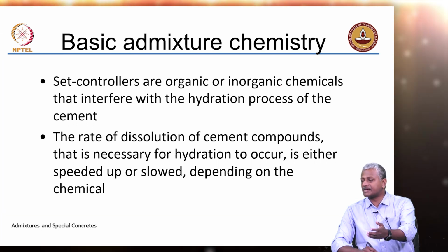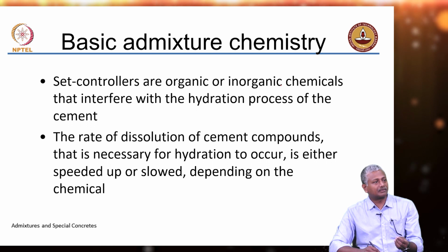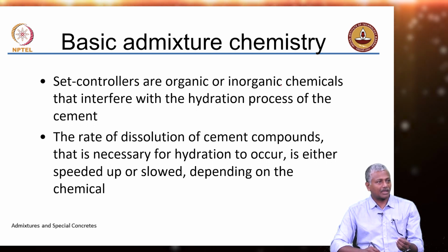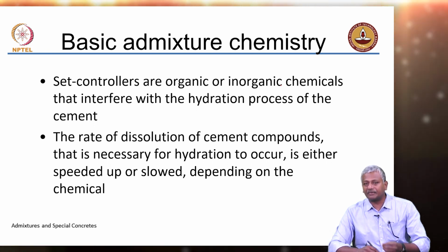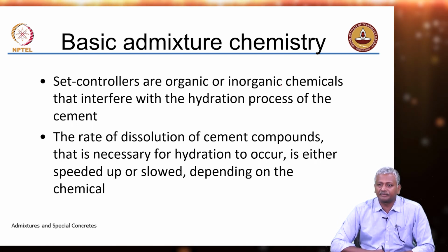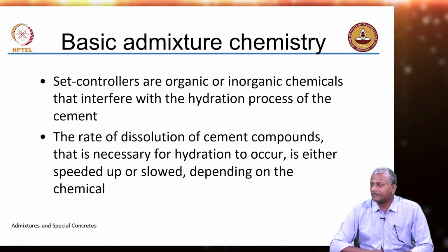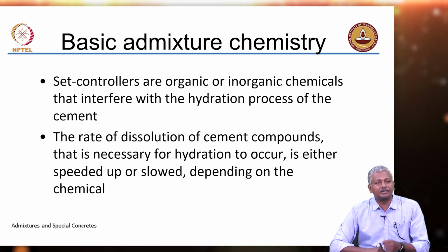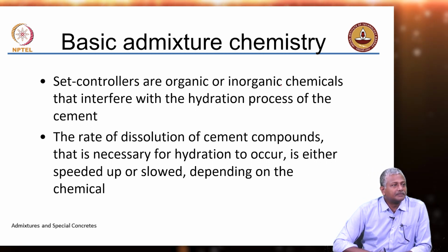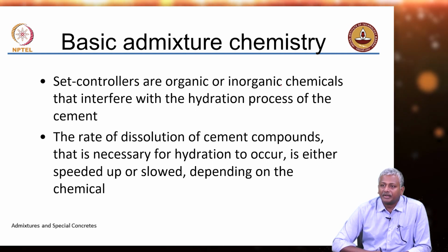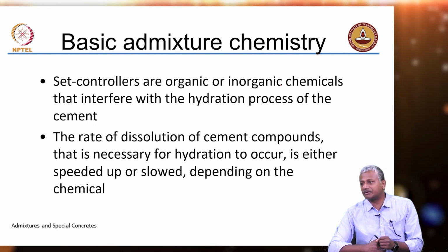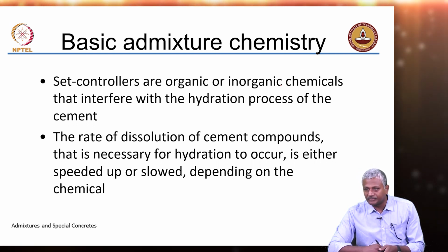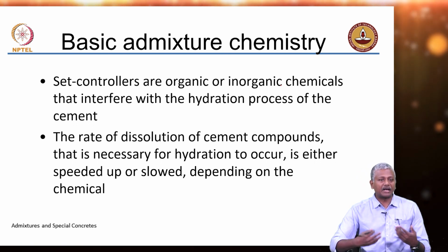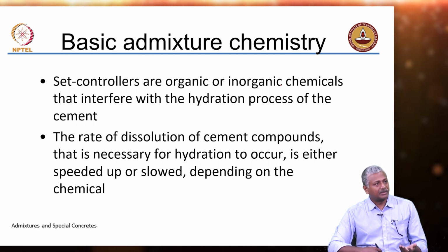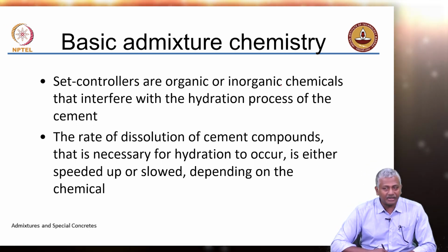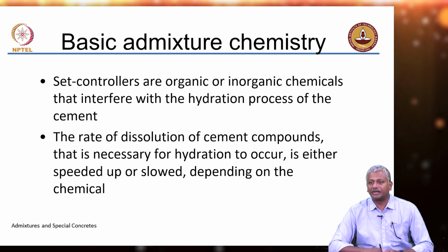Now, superplasticizers did not have a direct interference with the hydration process, right, but they did have an indirect interference. What is that indirect interference? Superplasticizers had an indirect interference. Why? They adsorb on the cement grains, prevent the cement grains from directly reacting with water quickly enough, right. So, the more admixture that you add, the more retardation that will happen. So, that is not a direct indication, but indirect indication of an ability to retard.